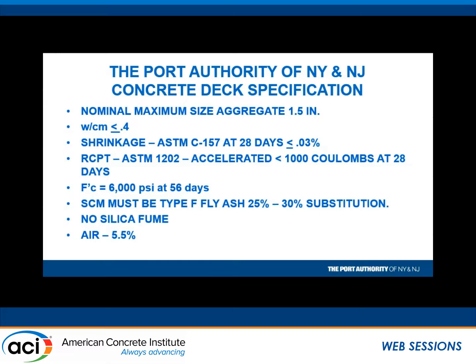So make a long story short, they would say, oh, this costs a lot of money. Well, I don't give a hoot about how much money it costs. You're going to do it. And we did samples for the rapid chloride permeability test every time we made cylinders. For every sample we did that, okay? And that's the way the job went. 6,000 PSI concrete, not a big deal.